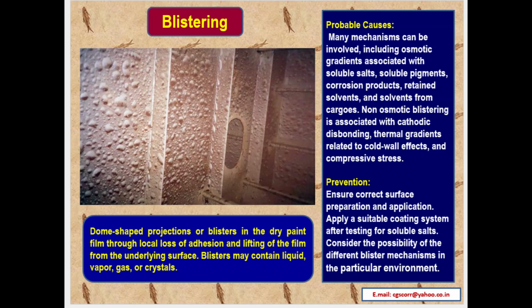The next one is blistering. The figure on the left top side gives you a picturesque view of the defect. Dome-shaped projections or blisters in the dry paint film through local loss of adhesion and lifting of the film from the underlying surface. Blisters may contain liquid, vapor, gas or crystals. Probable causes: